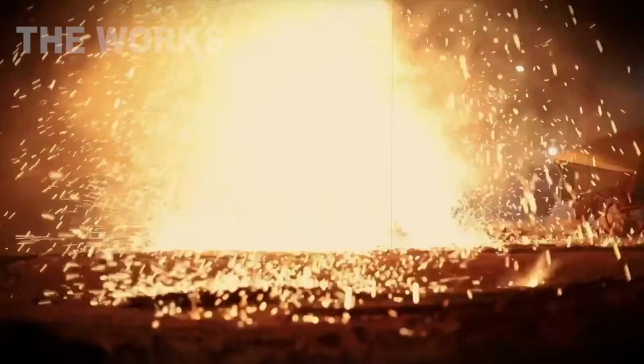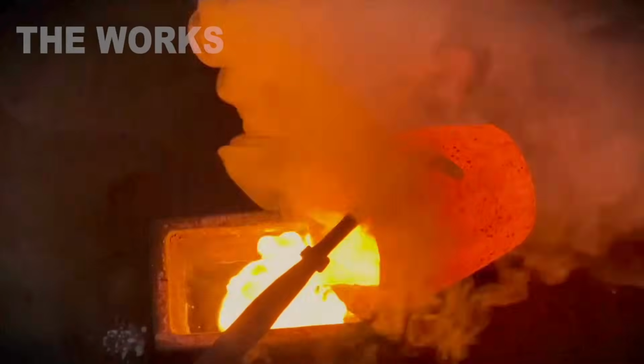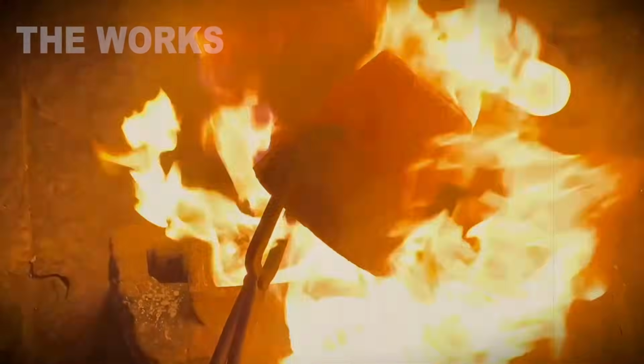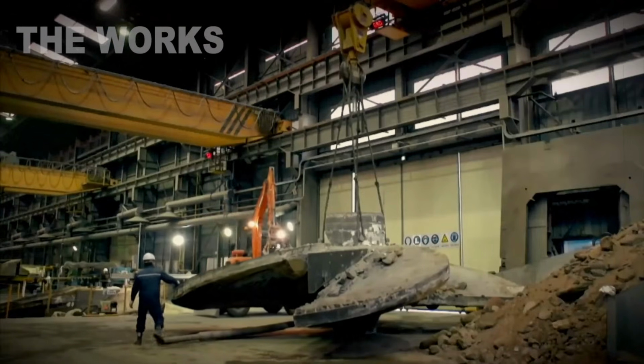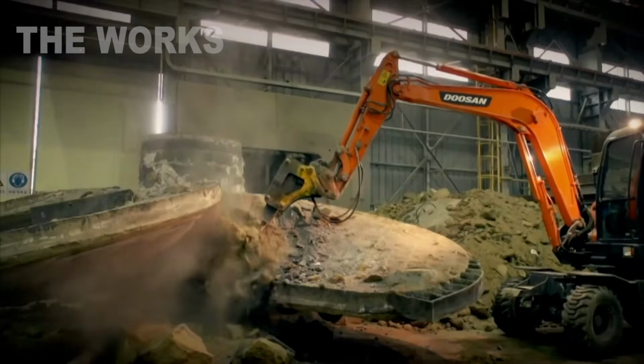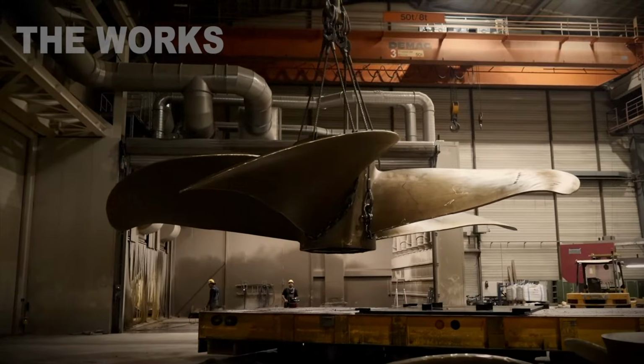When the mold is complete, they leave what's called a riser at the top, an extra reservoir of metal that feeds the casting as it shrinks during cooling. Without it, shrinkage cavities form inside the propeller, voids that would render the blade useless. The riser gets cut off later, but during the pour, it's a critical part of the process.